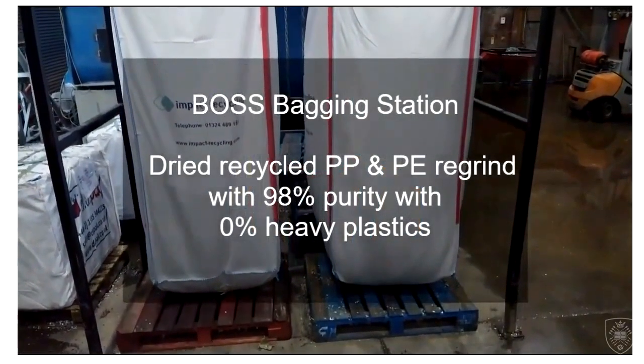So that was 2017, 2018, 2019, probably still today if I'm honest, but we're still getting that process better and better and better. And so we produced bags of pure polypropylene and pure polyethylene. And I think then we went to sell that, and we had a huge problem. That is a problem common throughout the whole of the recycling industry, which is not much talked about, but it's the melt flow rate, or melt flow index, of the plastic. Because we were taking in mixed post-consumer material, that means we have mixed melt flow rate. And the melt flow rate, for those that don't know, and I didn't know when we invested all this money and set up this plant, is the rate at which the plastic flows when it's melted.